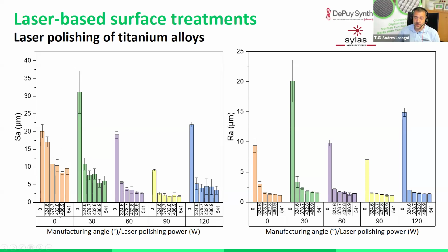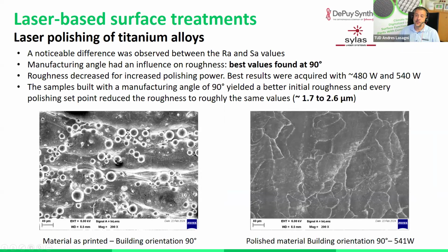And then depending on the way that the parts were manufactured, we can very strongly reduce the surface roughness, in this case, by increasing the laser power in the polishing process. So we are typically now reaching for this material alloy roughness values between 1.7 to 2.6 micrometers. So a very, very strong reduction.